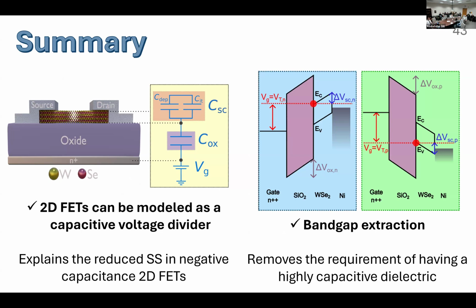Okay, so in conclusion, we realized that we can model our 2D field effect transistor as a capacitive voltage divider. This can help us explain the reduction in subthreshold swing in negative capacitance 2D field effect transistors. We can also use this method to extract band gap values from bipolar transfer curves. This removes the requirement of using a highly capacitive dielectric, which is not always easily accessible.